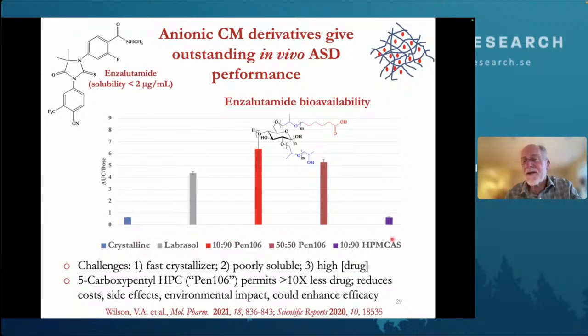This is an amorphous solid dispersion with that most popular current cellulose derivative, HPMCAS, at a ratio of 10 drug to 90 polymer, which is typical of ASDs. And it didn't improve on crystalline enzalutamide at all. It didn't help whatsoever. And it's because enzalutamide is a fast crystallizer. I told you that class of drugs has problems with current ASD polymers, and sure enough, this ASD polymer did not help it at all.